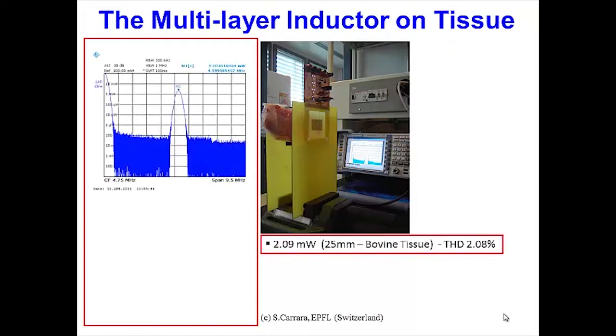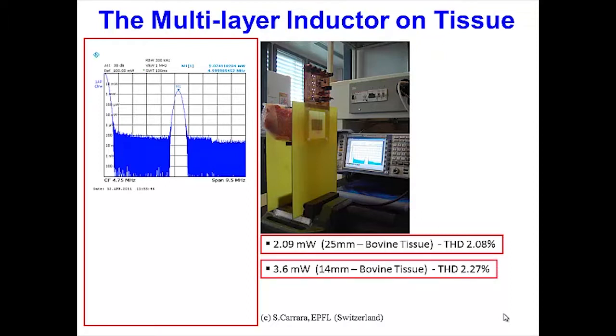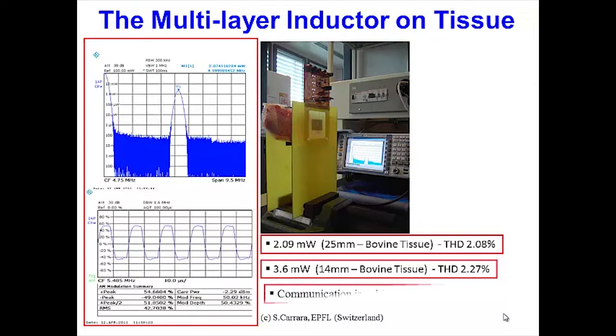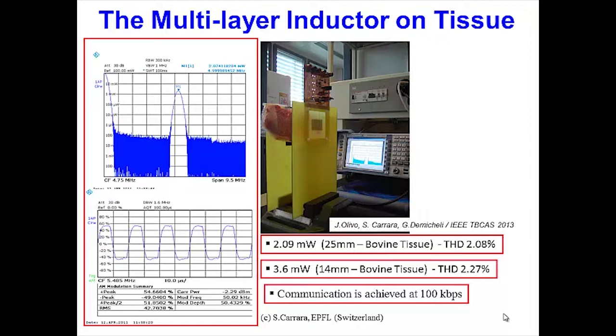We repeated the experiment not only in air with the best performing antenna, but also on tissue. We used a bovine tissue stack to perform the experiment, and we succeeded in receiving up to 2 milliwatts through 25 millimeters of bovine tissue, and of course if we decrease the distance down to 14 millimeters, we receive up to 3.6 milliwatts. A lot of room if we want to power our tiny chip, which requires only 230 microwatts. So it seems that it's really feasible to transmit power and so to develop such a complex device without any battery on board. We also checked the efficiency of the link not only for power transmission but also for data transmission, and we achieved quite a good rate, 100 kilobits per second.